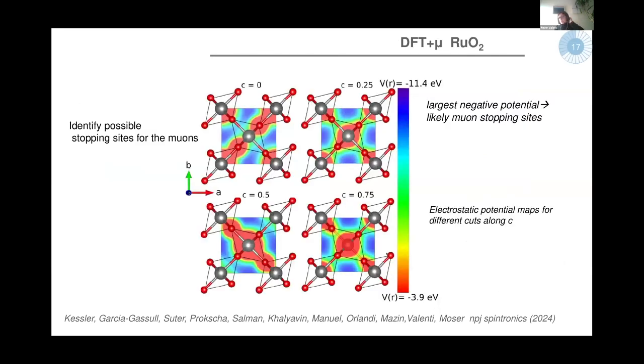We also tried to rule out a possible explanation, for instance some fortuitous or special coincidence whereby the muons maybe are not seeing the magnetism. So we also helped with DFT plus mu calculations, where one can first identify, by doing this DFT calculation, the stopping sites of the muons. The idea is to calculate the electrostatic potential, and where you expect the muon to stop is where you have the largest negative potential. We expected that to be far away from the ruthenium. These are the regions shown here in blue. So first of all, we know where we expect these muons to stop.